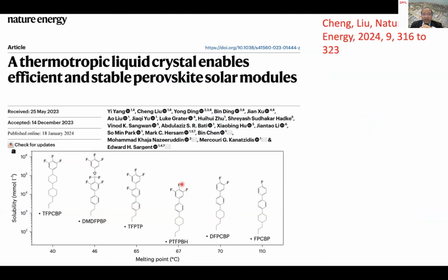Let's take the one example that has 3 fluorides. I mentioned that fluoride groups are important to replace the iodide defect, to passivate the iodide defects. And you have an aliphatic chain in the molecule here, which is hydrophobic. And it is a liquid crystal at room temperature, and liquid crystal at the temperature where you're processing your perovskite film. Now you put this material in your perovskite solution. When you process the perovskite film, this liquid crystal is uniformly distributed throughout the perovskite because it's a liquid at the temperature where you are sintering.